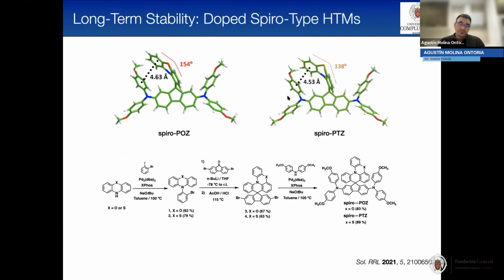Well, just to finish, we wanted to move away from the flat land of these central cores, and we wanted to explore molecules with higher solubility. In this case, we selected this spiro-type hole transporting material based on phenoxazine and phenothiazine. For the synthesis with phenoxazine or phenothiazine, we perform first a Buchwald-Hartwig reaction. Finally, we treat it with butyl lithium and quench it with this ketone. We can obtain the spiro core. Finally, we introduce the diphenylamines by a twofold Buchwald-Hartwig reaction in very nice yields.